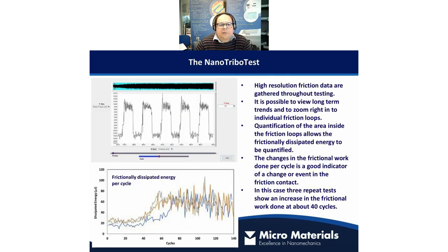So this is what the data looks like, just a few screen grabs here. This is time of the test along here, and these are our friction cycles. So these are our friction loops: that was sliding along, then the other direction sliding along, okay? And we can turn these into friction loops. This is a macro scale view of the whole frictional history of the test.